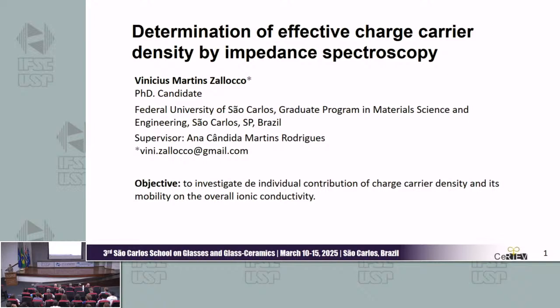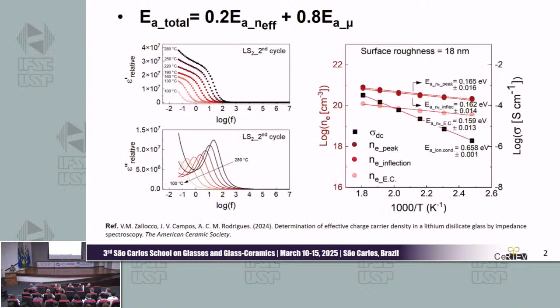We study ionic conduction in solid state for solid state batteries. Today I'm going to show you one of the works of my PhD, which is the determination of effective charge carrier density in lithium disilicate by impedance spectroscopy. The main objective is to investigate the individual contributions of charge carrier density and mobility to the overall ionic conductivity. We did this using complex permittivity on the left.